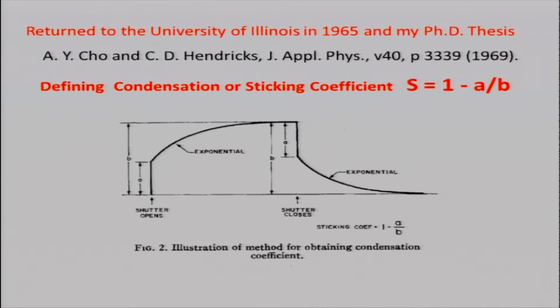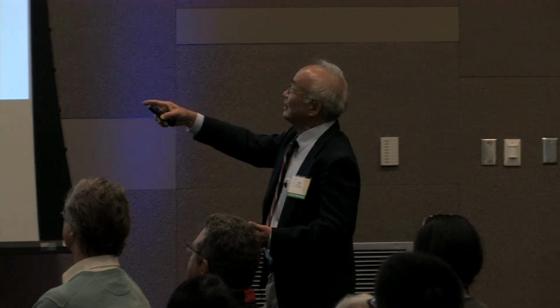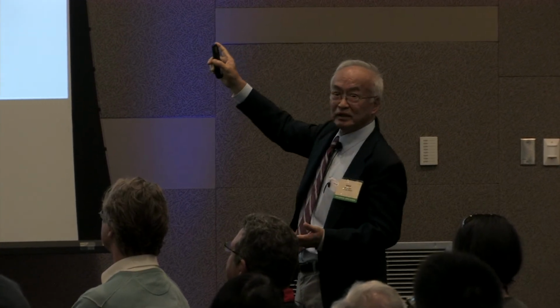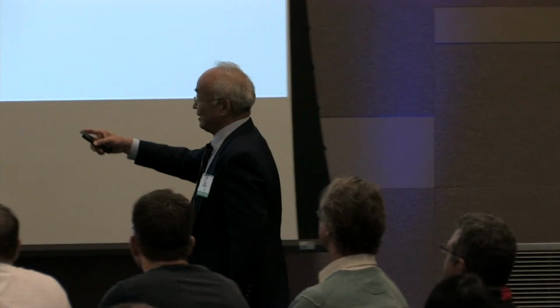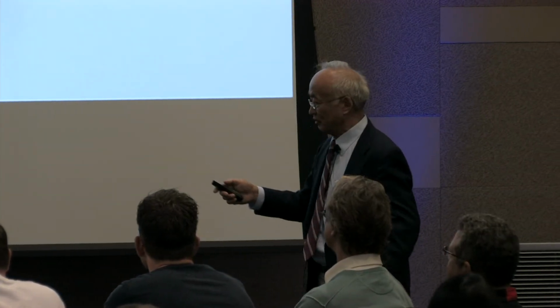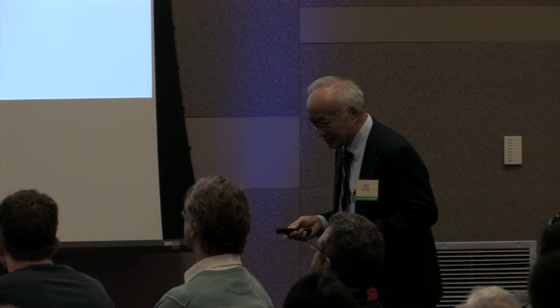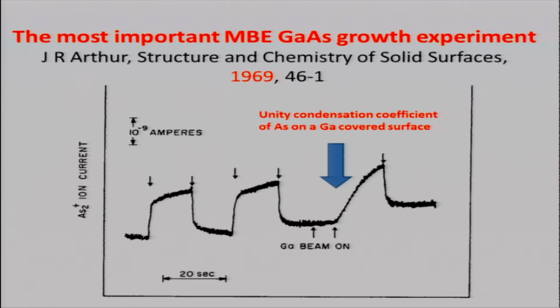If A equals B, then the sticking coefficient is 1 minus 1, 0. There's no atom adsorbed on the surface. The other extreme, if A equals 0, then the sticking coefficient S is equal to unity, 1. That means every atom you hit on the surface sticks. Of course, in between, there can be a fraction adsorbed, 0.2, 0.5. Now, with this, John Arthur made the most important study of the surface physics in adsorption, desorption work.